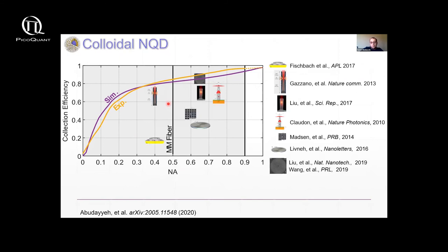And we also compare this to current literature. What's out there, what people already measured in terms of collection efficiency. And we see that our device is performing very well compared to literature. One essential thing to note here is that most of these devices are for devices operating at cryogenic temperatures. Due to the broadband emission of our structure, even with the broadband emission we can get very high collection efficiency. So this is something very impressive.